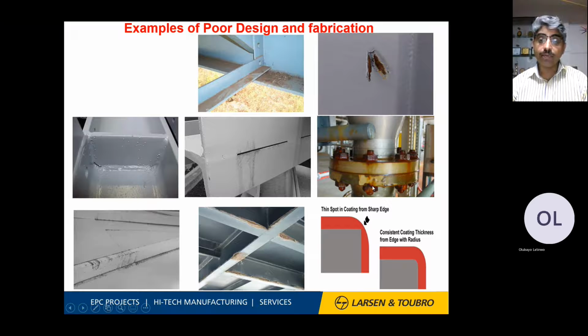Or sometimes dissimilar metal weld or dissimilar metal joints, we can say the bolt material and the flange materials are different. Because of the galling effect, they always choose low alloy steel material for stainless steel joints because of its high strength, and that is leading to poor design based on the corrosion resistance properties of the bolt. And sometimes it is difficult to even open during shutdown. Similarly, if you do the welding on one side and leave the other side unattended, it is going to create problems with the structures.